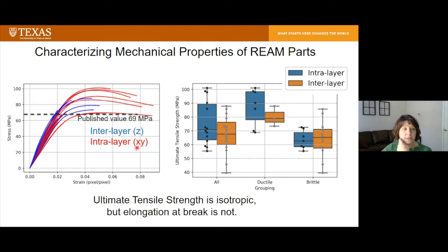One of the things you'll notice is that almost all of the parts meet or exceed the published value for this particular resin, which is really quite good. Another thing you'll notice is that the red parts, the ones within the layer, appear to have a greater elongation at break. We'll dive into that a little bit more.